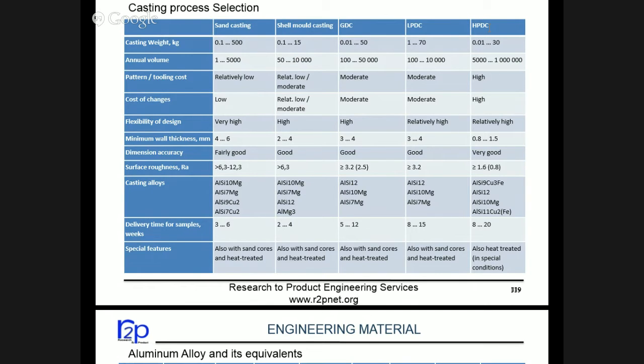Property wise, for GDC and LPDC we are able to achieve similar material properties, because both are heat treatable, right? But the only thing is LPDC yield is more. So that is the main selection criteria. And surface roughness, of course, HPDC is best. You can see it on all the bikes and others. The surface roughness is very good, and a wall thickness of up to 1.5 or 0.8 mm is possible.